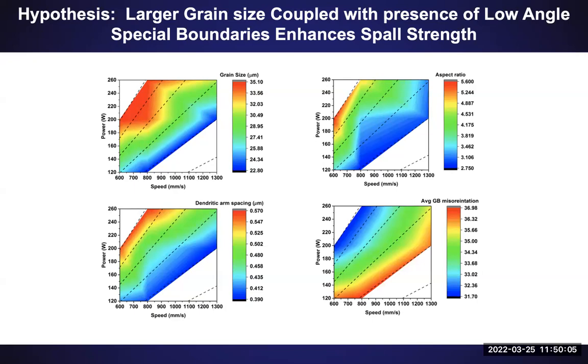So Luis, to be honest, I kind of glossed over that part too, because one thing we had measured was also the dendritic arm spacing in these samples. And if you look at the plot that's here, we didn't see any specific correlation there. So even though we measured that, we don't think that was the reason why we were getting a better spall strength in the material. We measured it to see if that would influence things, but it didn't seem to.